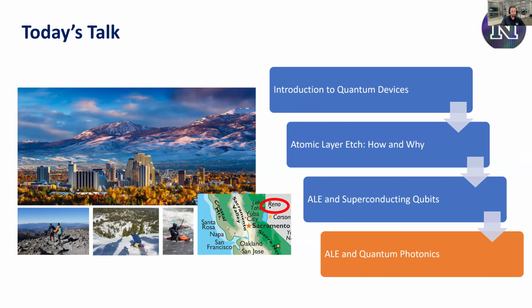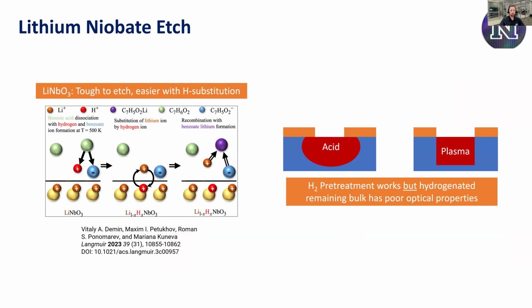This is some work that I was involved in with Caltech when I was at Oxford Instruments. Lithium niobate is a really tough material to etch, but people have been doing something called hydrogenation for a while. You can do hydrogen substitution and get rid of some of that lithium, and you can actually make the material etch much more easily.